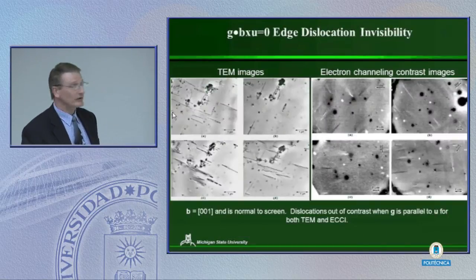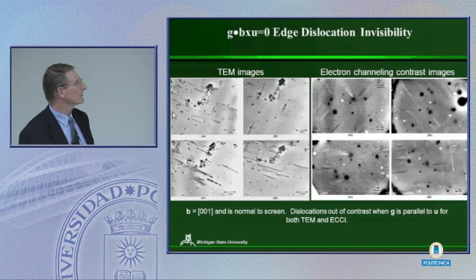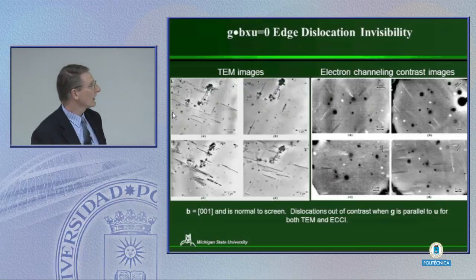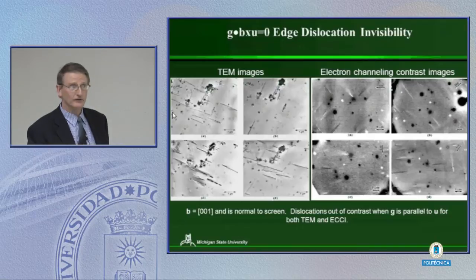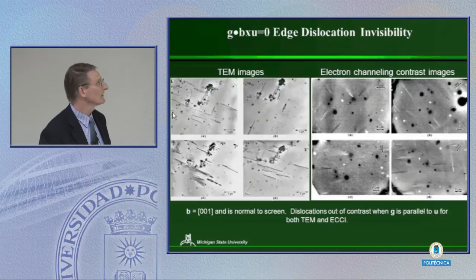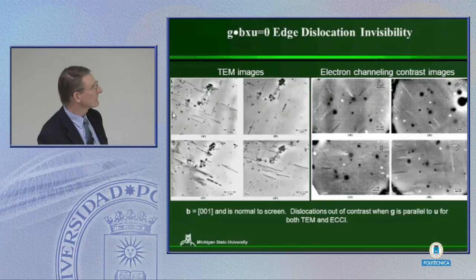These are the only TEM images I'm going to show you, but there's a reason for this because I want to demonstrate the G.B cross U criteria. What these are are prismatic loops in iron aluminum. The Burgers vector is 001, which is coming out of the board. And so when we look at these dislocations here, A and B, those both have the same Burgers vector. The critical thing is, depending on your G vector, when your G vector is parallel with the dislocation line, those dislocations go out of contrast. And we can see that both here with the 020 and here with the 200 reflections.